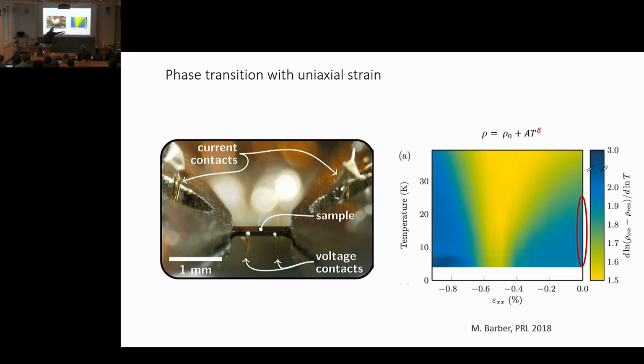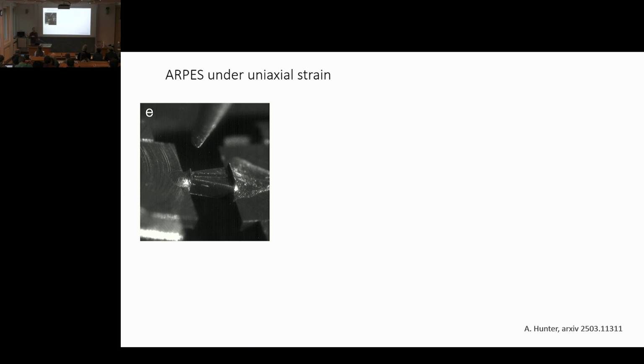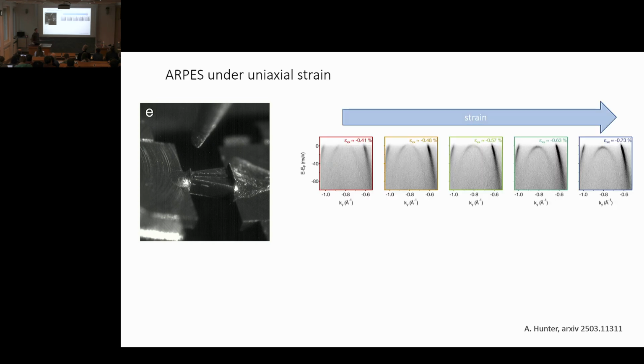If you move with higher and higher strains towards this value, we see that even at cold temperatures, we change from our T squared law to about a T to the power of 1.5 law. And with ARPES, we want to know what actually is going on at this point. So we somewhat repeated this experiment. We also have our crystal here, and we pressed from both sides, applying uniaxial strain. And what we saw is that we have this band in particular, which seems to move lower and lower until it crosses the Fermi level.